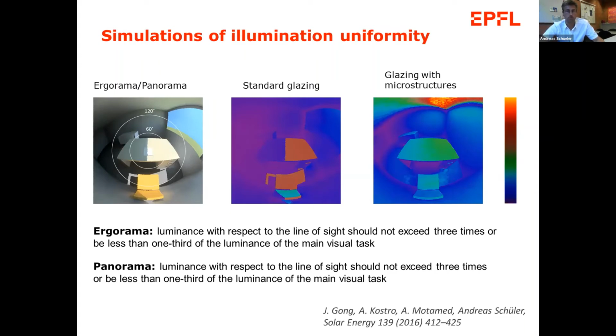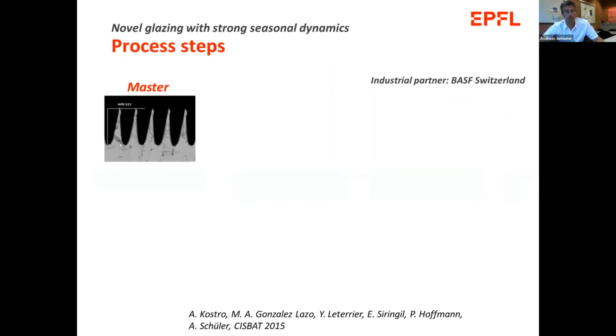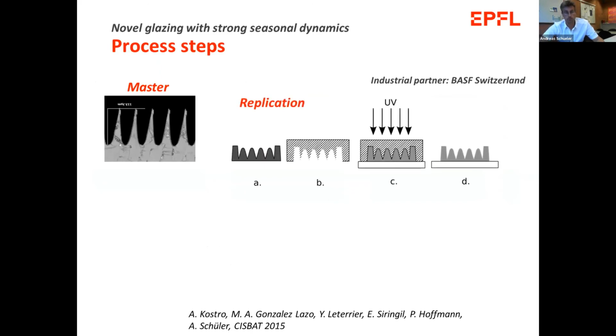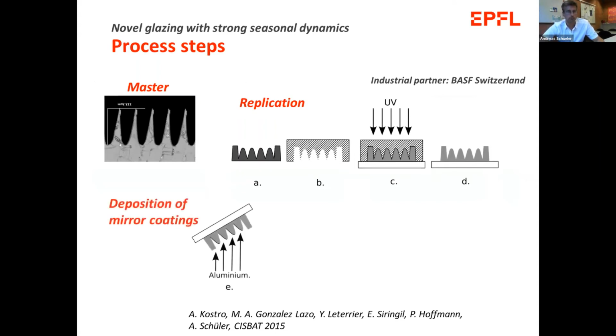Furthermore, we also believe that we can have strong advantages in glare protection for the direct glare. So we have to work out a procedure of making this. We would start with the origination of a master mold. We do this by laser ablation. We create this microstructured master. We would then replicate the master. This is done with UV curable resins. Then we have the replicated microstructure. We would deposit mirror coatings on one side of the structures, and finally encapsulate the mirrors. And then we would have the fully embedded mirrors in our glass pane.